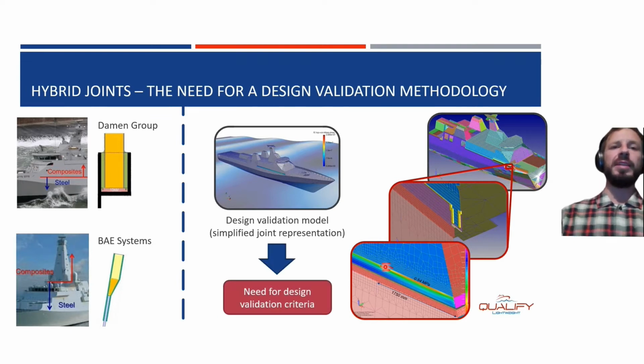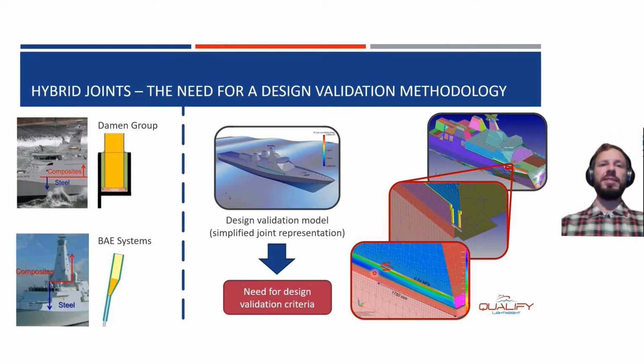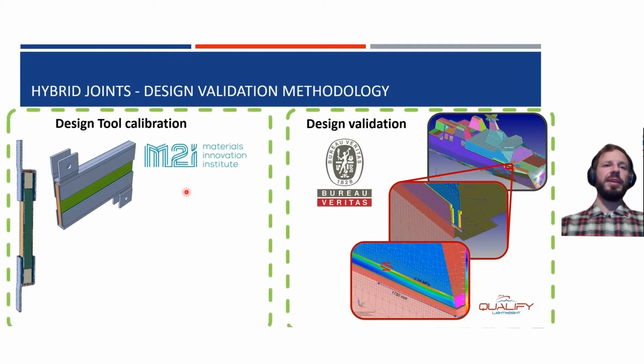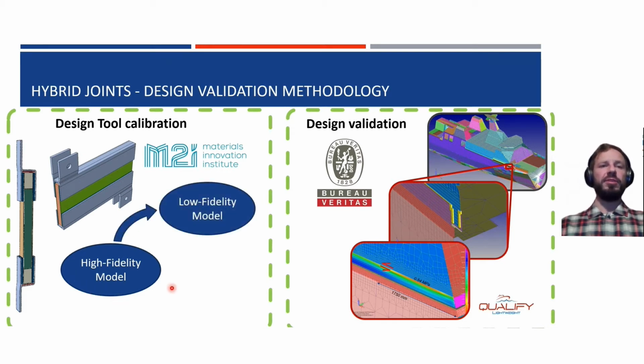So we actually need some design validation criteria in order to assess the strength of this joint and its safety. For that, within M2i, we developed a high fidelity model approach, which is based on the large scale samples, as has also been experimentally tested. Using those high fidelity models, we use a methodology to create low fidelity models that are representative for the design validation model. Using then a transfer methodology, we can get insight into the safety of the joint.